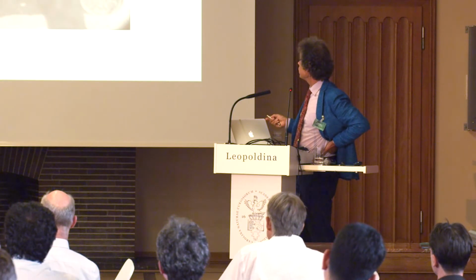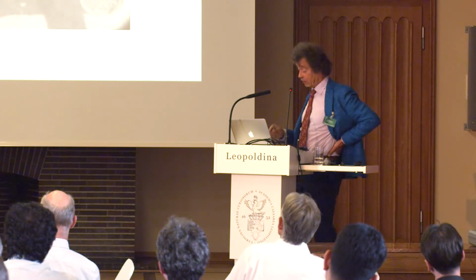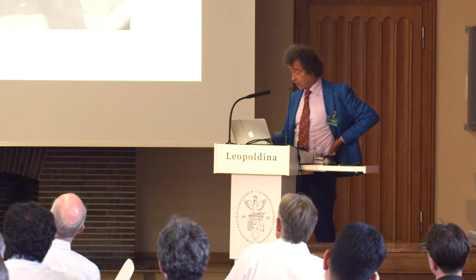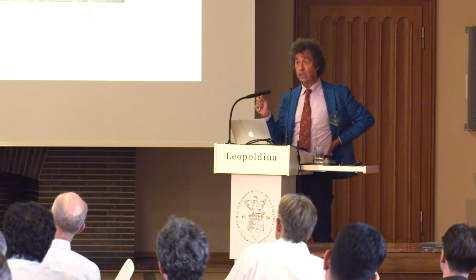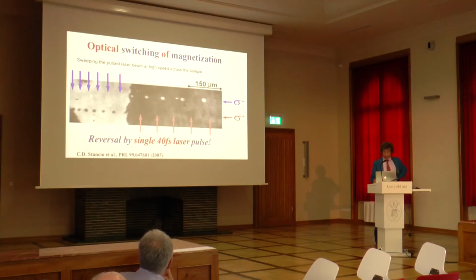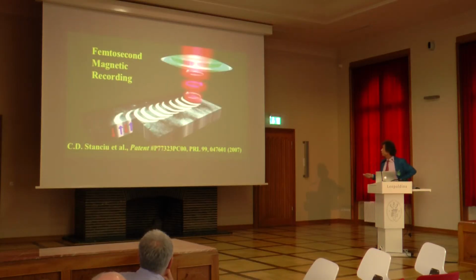And now these are lots of pulses, 40 femtoseconds, so very short, but with a kilohertz rep rate, and it moves slowly, so you cannot see what an individual pulse does. But if you do this very fast, then you find that you can indeed write individual bits with a laser. And so we use that to write magnetic bits.